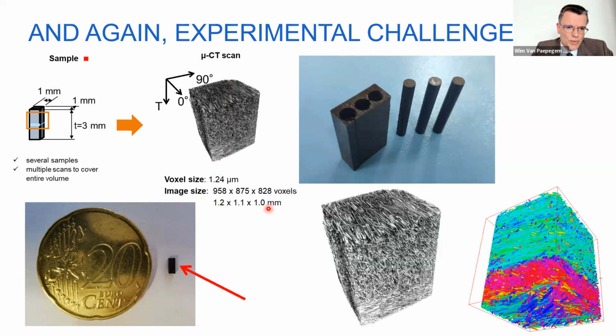Now, if you don't want to lose your hands or your thumbs in the diamond saw, then even cutting these samples is already a nightmare on itself, because in this case it was thermoplastic. So also the heating that you introduce by cutting should be minimized. But now we managed to make very small samples here. For those who are in Europe, you will recognize the 20 euro cent coin. For the others, you have to believe me that this is about 1 millimeter size. And this is a small coin in euros. And then we can do a CT scan, and indeed, by deep learning algorithms, we can segment the individual fibers and get some statistics on the fibers.